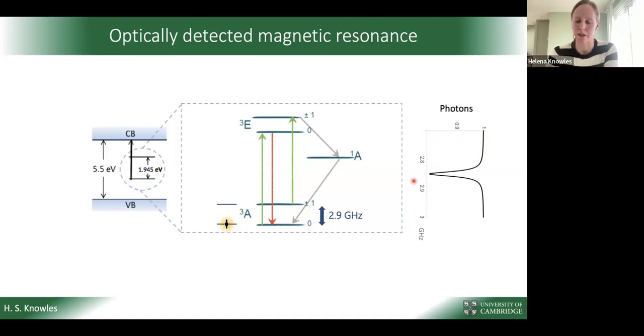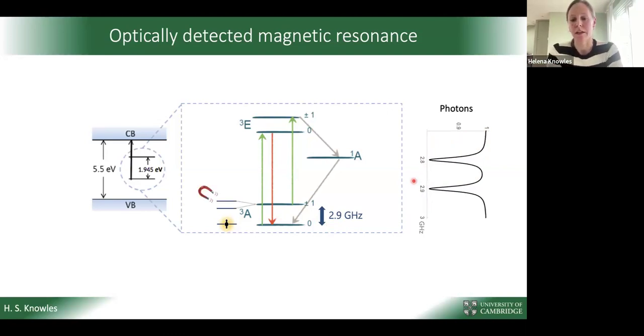Well, it turns out that a lot of the quantum sensing schemes, especially in biological systems, are based on exactly this technique. If we apply a perturbation, in this case an external magnetic field, the plus and minus 1 levels split apart, and we will see this as a feature in the resonance. From the splitting of these resonances, we can extract the energy level spacing, which then relates to the magnitude of the perturbation.